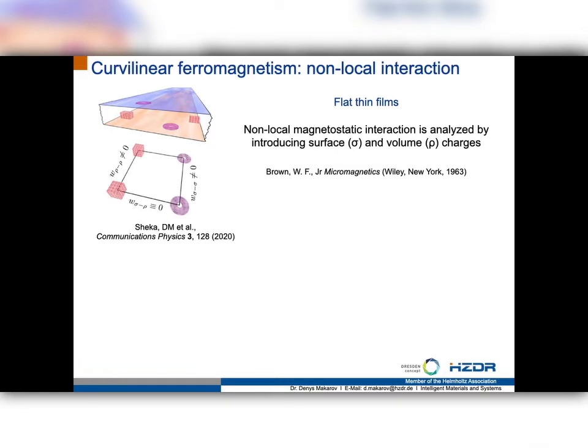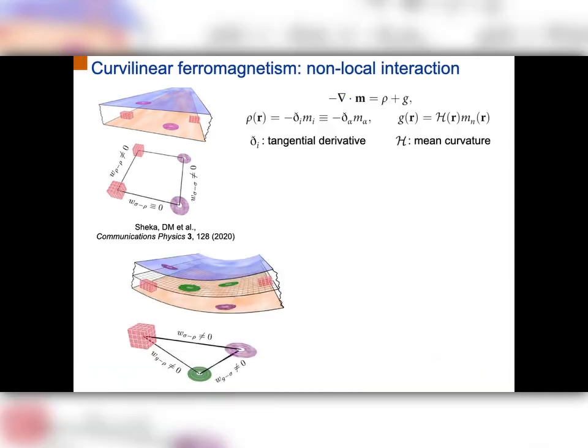If you have a thin film with equal interfaces at the top and at the bottom, the interaction between surface and volume charges is allowed, but it's trivial, so it's basically canceling out, and this energy term does not give any contribution to the energy functional. What will happen in the curved thin films, because you have loss of symmetry because of curvature,